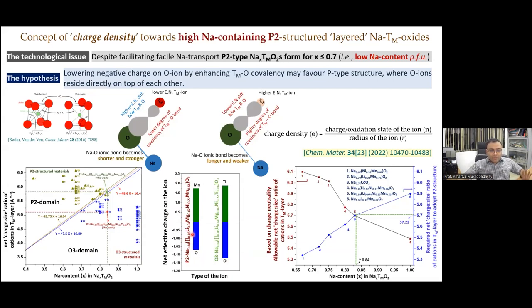But again, there is one catch here. While we say that if we increase the charge to size ratio in the transition metal slab, we will have the P-type structure more stable, yes, that is the case, as also revealed by DFT. But then if we keep increasing the charge to size ratio, charge neutrality will force us to reduce the sodium content. So there has to be a balance. So based on such a balance, we designed one composition, which is mentioned here.